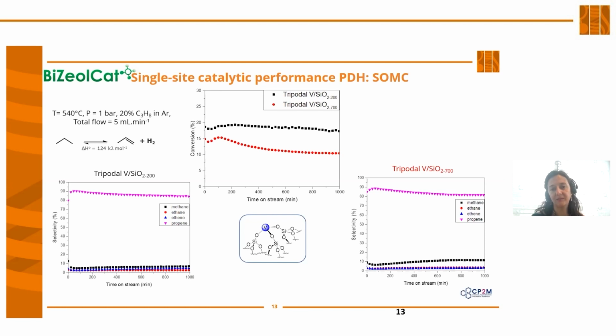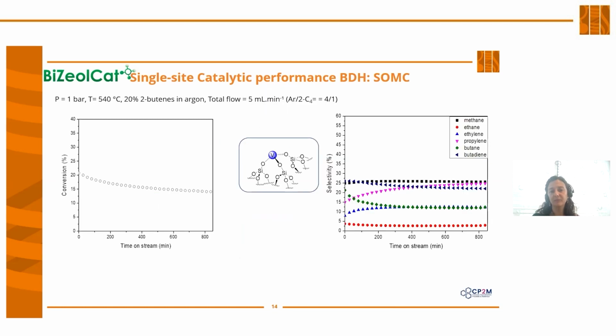This catalyst can be used, as we've seen, for propane dehydrogenation, but it can also be used for butene dehydrogenation. As you can see here, the best catalyst for propane dehydrogenation of this series was also tested for butylene dehydrogenation, and we can observe that after 400 minutes the conversion is stabilized at around 15%, and the selectivity remains high to the butadiene and stable throughout the test time.